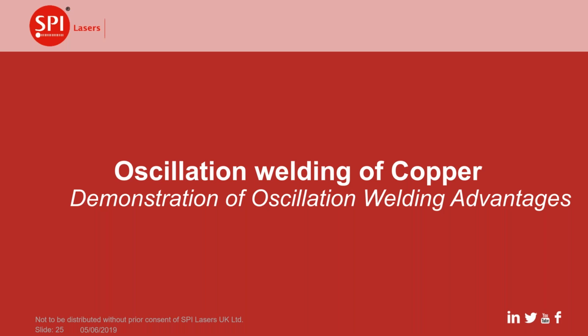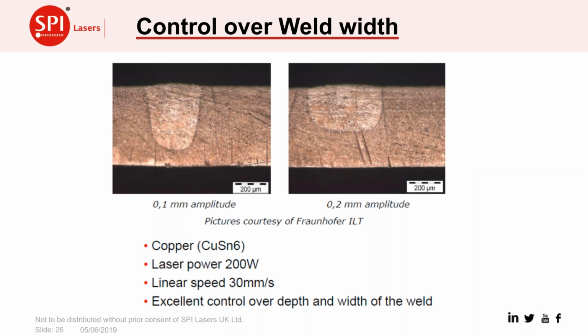I want to show some results now from oscillation welding for different materials, starting off with copper. This one was done at quite low power, but you can see that just by changing the amplitude of the diameter of the weld, it was very easy to change the profile. This is one done by someone we were working with.